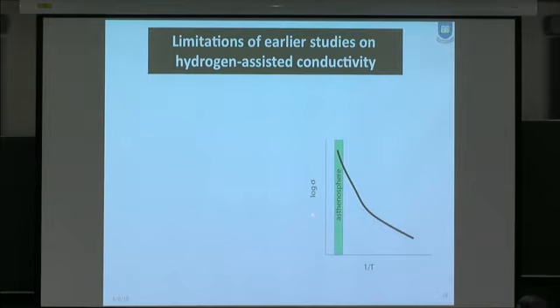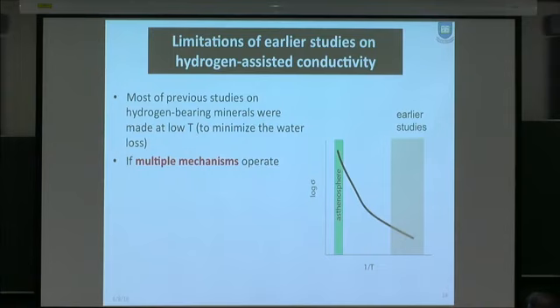The point is, properties such as electrical conductivity, if you plot against 1 over temperature, this is a low temperature range, and this is the high temperature range. Earlier studies were conducted in the low temperature range because they didn't want water to go out of the sample. At high temperature, quite often water goes out of the sample. So they limited their measurements to low temperature. However, if multiple mechanisms exist, then extrapolation from low temperature to the high temperature range is not justifiable. If you extrapolate like this, you would calculate this much conductivity, but if a mechanism change occurs like this, the actual conductivity is much higher. So the extrapolation is not justifiable if conductivity mechanisms change.